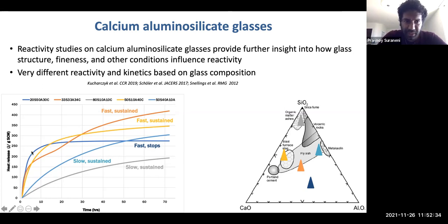So the first 3 here, these are fast. The bottom 2 here, which are actually high in SiO2, Al2O3, or low in calcium, these show very slow reactivity. But these two show sustained reactivity, right? The slope, if you can look at that, keeps on going. On the other hand, the composition which is very low in SiO2 increases very rapidly, but then it essentially stops. That's this composition.